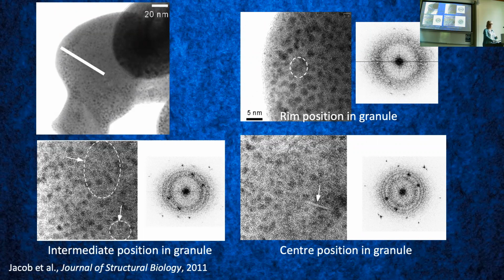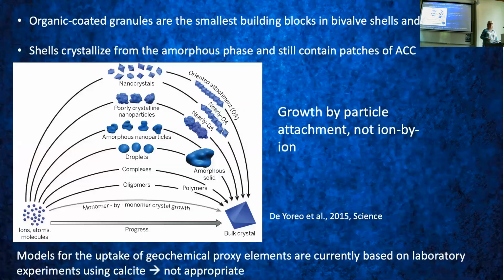So that was a big learning experience in that project, and it wasn't our first electron diffractogram that we produced there. Anyway, what we showed, and that was really the new thing about it, is that mother of pearl actually consists of these organic-coated granules as small building blocks in every one of these aragonite tablets. And that the shells in fact crystallize from an amorphous phase, and that's why they still contain patches of amorphous calcium carbonate, or ACC.